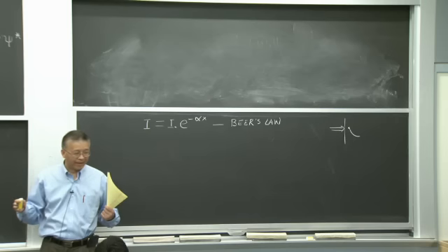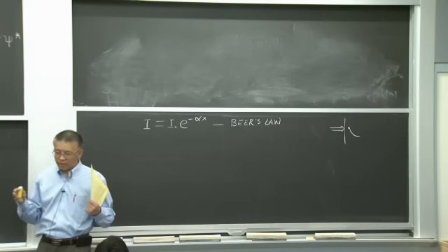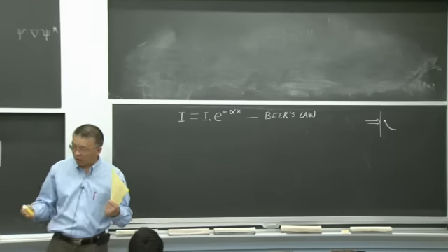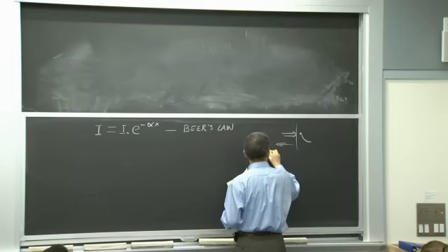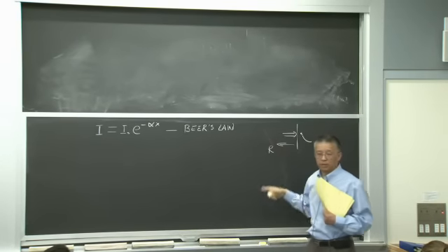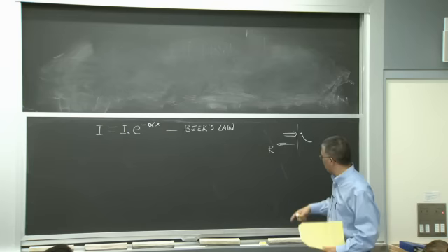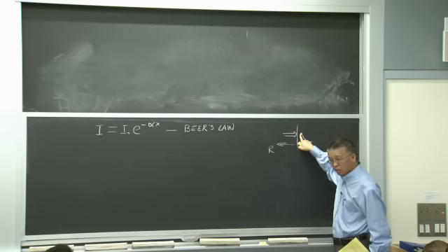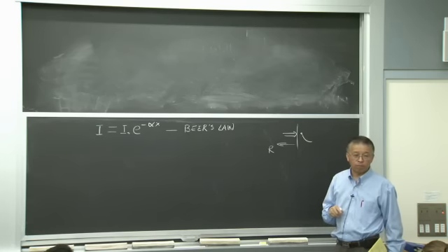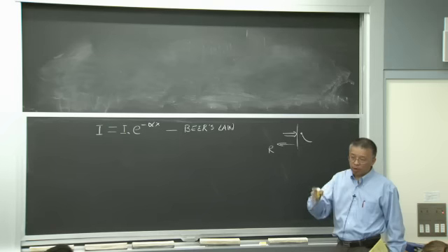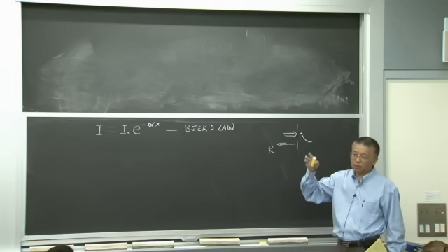What does that mean? It's conflicting, right? What that means is the reflectance R is very large. A material could be 99% reflecting. But once the electromagnetic wave gets into the material, the penetration depth is very short. Those that get into the surface are absorbed in a very short distance.